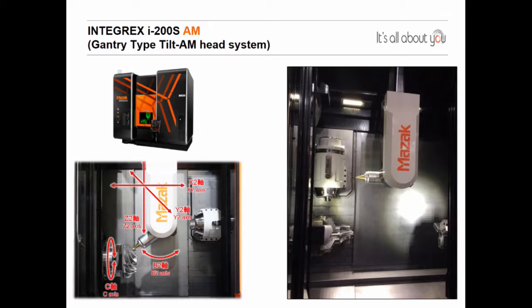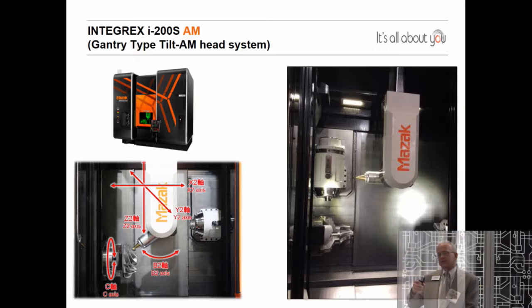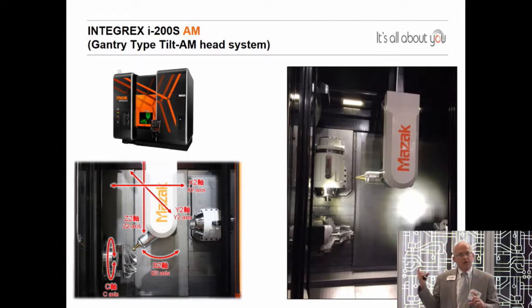This gives you an image of the inside of the machine along with the rotation of axis of the additive. What's really nice about this is if you notice the x-axis stroke on the current milling spindle is limited to how far I can go up in x. But if you look at the gantry style, I have much more x-axis stroke, so my build process has just increased. In most applications, you're limited on the milling spindle of how big of a part you can actually make. Now, I think normally on the Integrex it was only about 13 inches. With this design, we can get up to about 26-inch diameter additive.